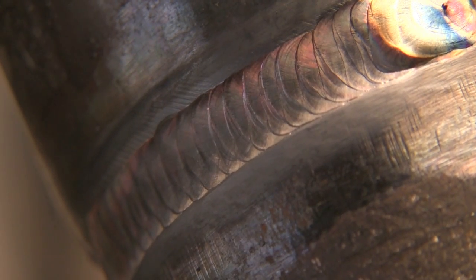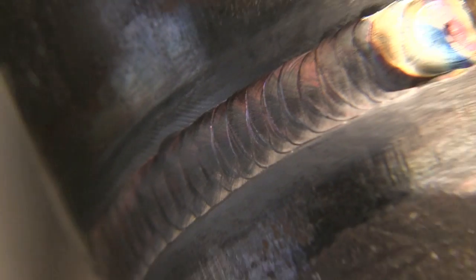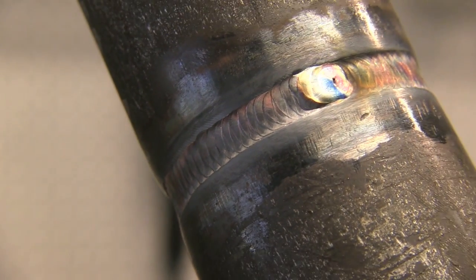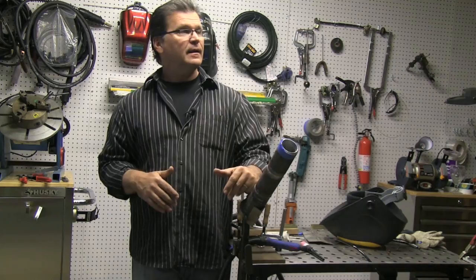You know, if you can go across the middle as quick as you want, but if you don't hardly progress forward any, then you're just going to hang in one place too long and the heat's going to build up and you're going to have problems. So it's all relative. It's not just amps, but it's travel speed and how fast you go across the middle and how much filler rod you add.